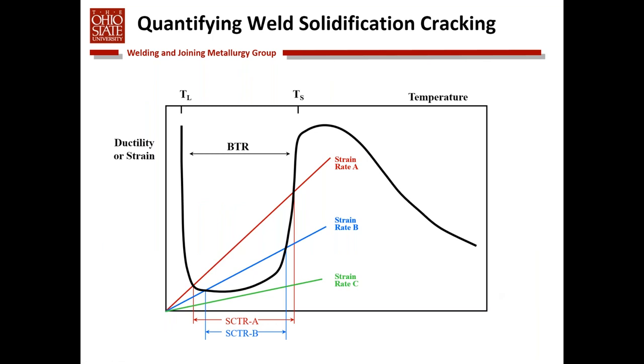So how do we quantify weld solidification cracking from a fundamental standpoint? Well, one of the things that we want to do is be able to quantify what we call this brittle temperature range. And so this is the drop in ductility that occurs over the range of solidification. So at the liquidus temperature where the material's 100% liquid, it has basically infinite ductility. Once it becomes 100% solid at elevated temperature, it also has very high ductility. But in the temperature range in between, within the solidification temperature range, we see this drop in ductility.